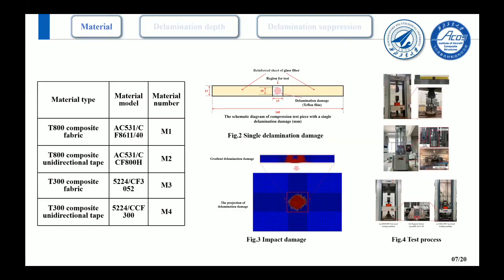Firstly, we will compare the effect of delamination damage on the residual compressive strength of different composite laminates. Subsequently, the influence of delamination depth will be investigated. Finally, in an effort to mitigate the detrimental effects of delamination on the mechanical performance of the laminates, we will explore the application of a discrete toughening strategy to suppress its growth.